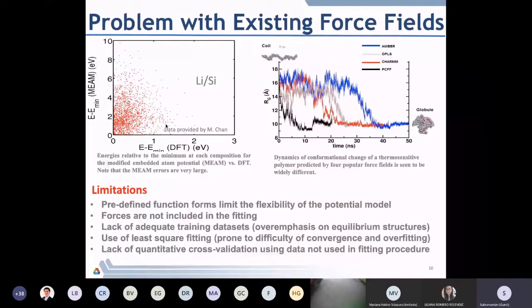The other aspect is dynamics. So we have basically a thermosensitive polymer that is undergoing a collapse from a coil-like state to a globular state above its lower critical solution temperature. So this is an expected behavior. Above the LCST, or the lower critical solution temperature, this polymer will undergo a collapse. All the 4 force fields that we simulated, this same polymer, show the expected behavior. But the dynamical evolution is completely different depending on what force field you use. So with all these time-resolved techniques that are now coming up, the question is, which one of these force fields are you going to trust?